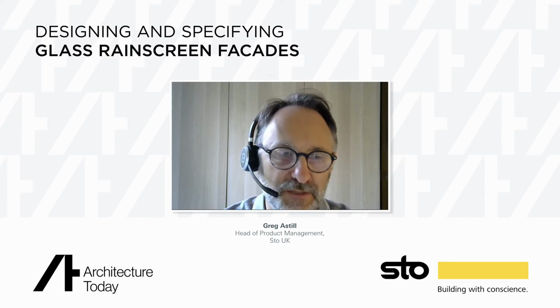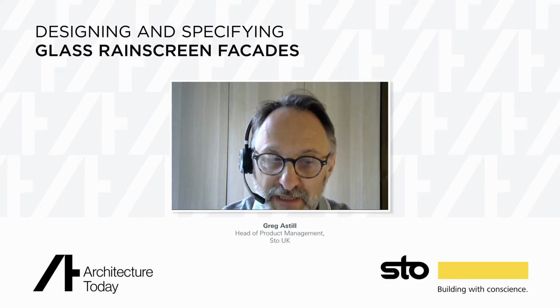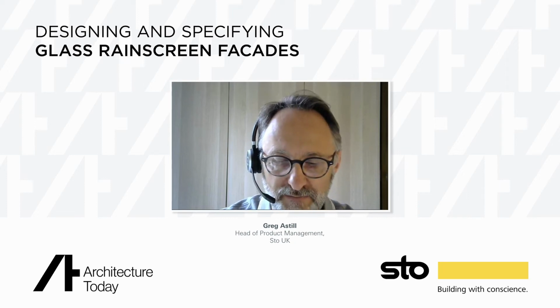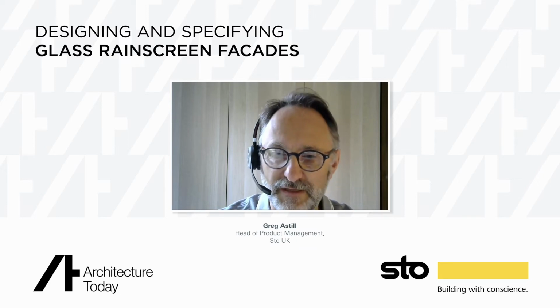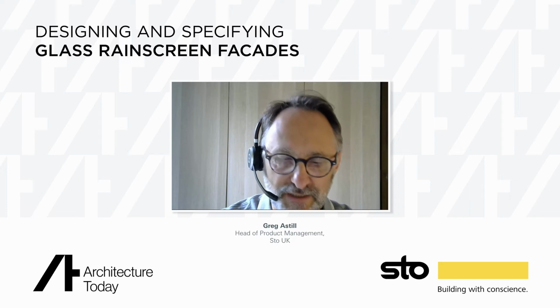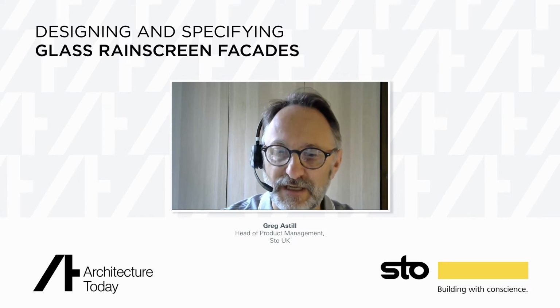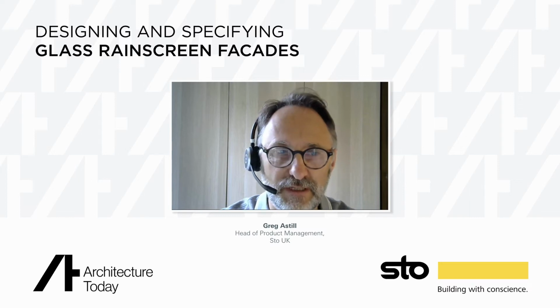The glass panel itself, the colours: typically we'll go off a RAL colour chart. That's typically our main basis for colour, and the pigments used by the process. By virtue of the manufacturing process, the pigments are fused into the back of the glass panel during manufacturing. That happens in the glass kiln, when the toughening process is underway. So those are mineralic pigments.